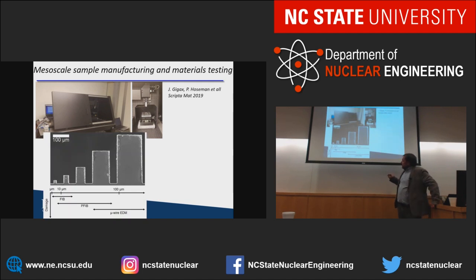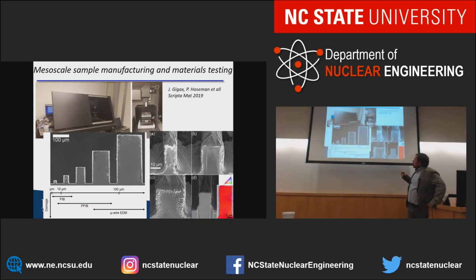So here's pillars of different length scales, manufactured with our collaborators at Los Alamos National Laboratory, Jonathan Gigax and Stu Maloy. And cutting these pillars with a laser takes minutes, not hours, like on the FIB. And so you can very easily make those mesoscale features. Now, it's not as nice as these other pillars I showed you earlier. They're rougher on the edges, and there's probably a little bit more damage from this faster cutting. But the question is, does it matter? Does that damage actually matter?